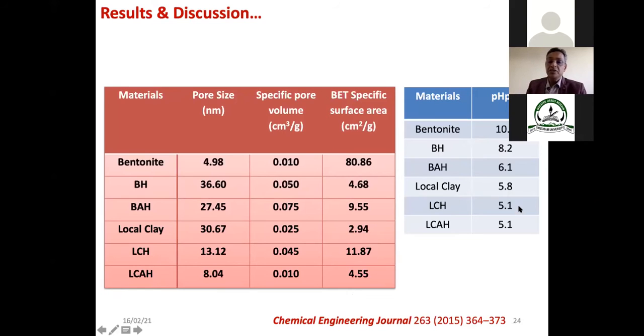The point of zero charge is a very important physical quantity. Above that pH the surface is negatively charged, and below that pH the surface is positively charged. Now you see that bentonite has a point of zero charge of 10. When you have modified it, say BH, meaning HDTMA, hexadecyl, has been introduced into the bentonite, the PZC decreased to 8.2. When you have pillared it with aluminum and then introduced the organic molecule, HDTMA, the PZC is now 6.1. The local clay was having 5.8, 5.1 and 5.1. You can see this 6.1 is close to the neutral pH, so the material is more useful. You can use it around neutral pH for different purposes.